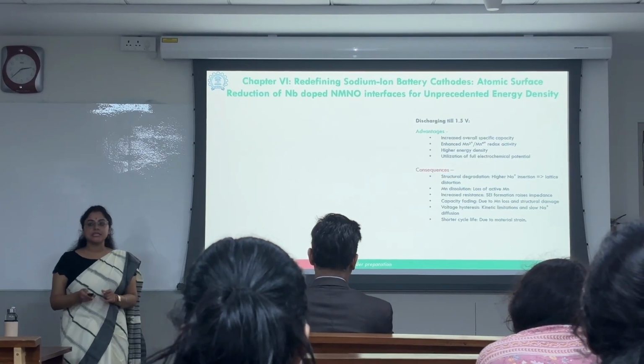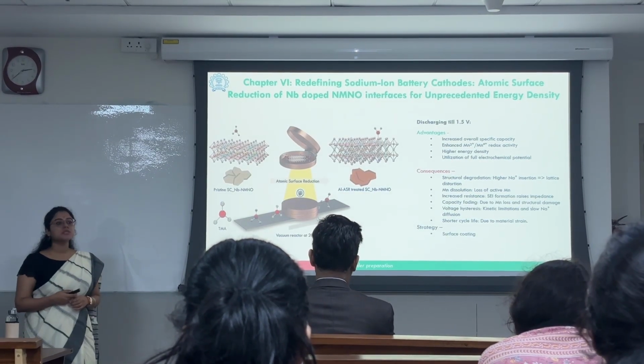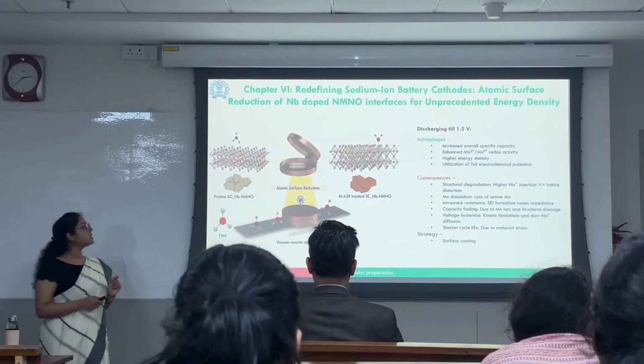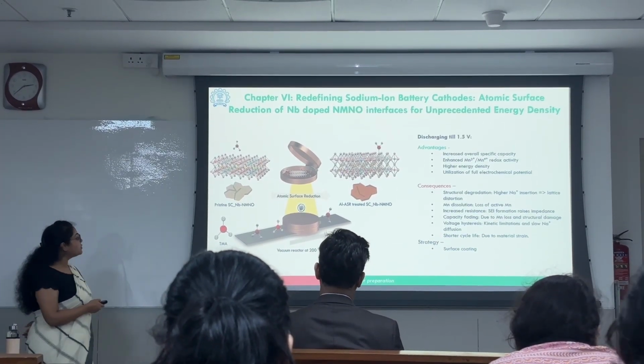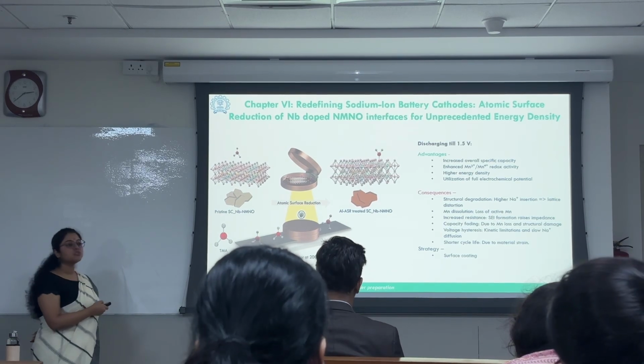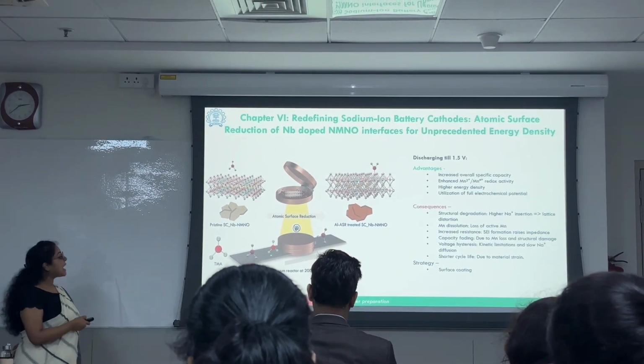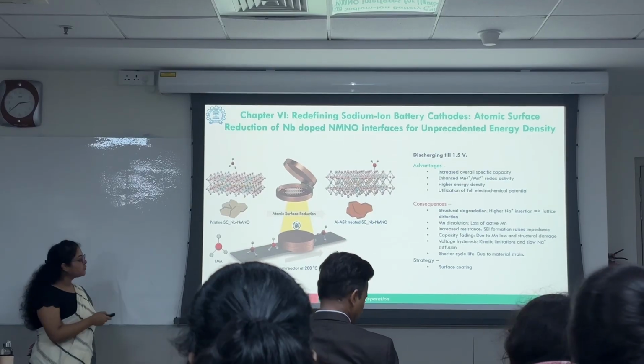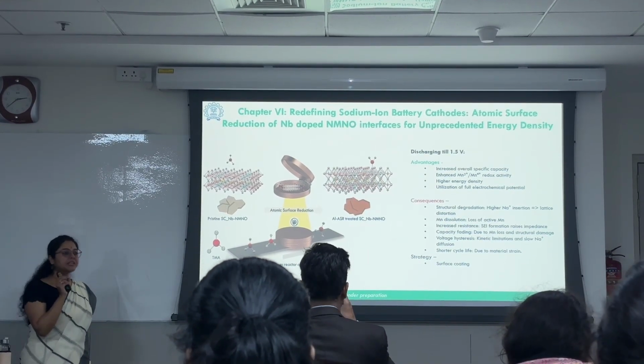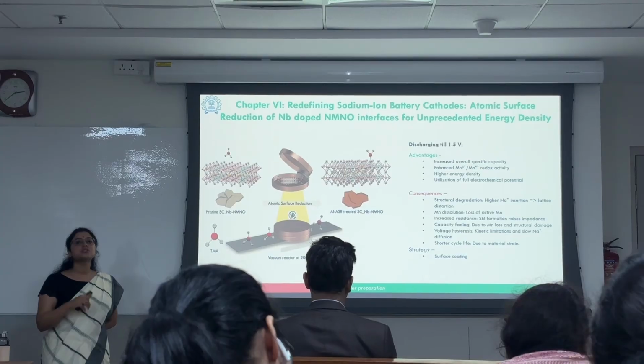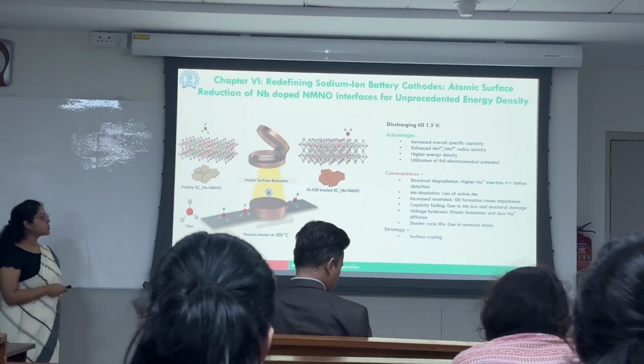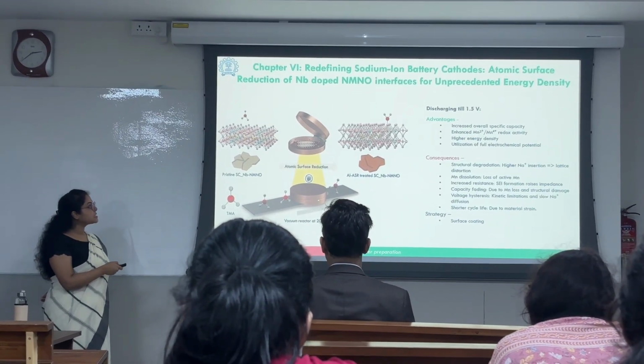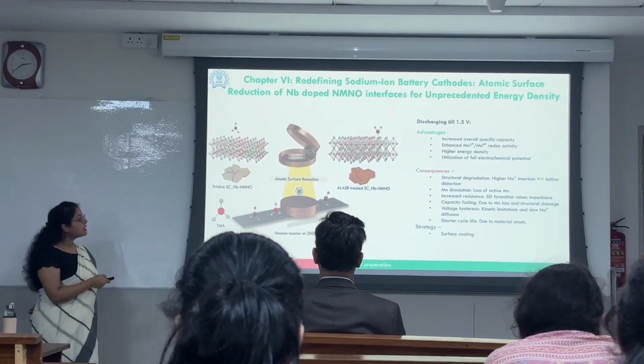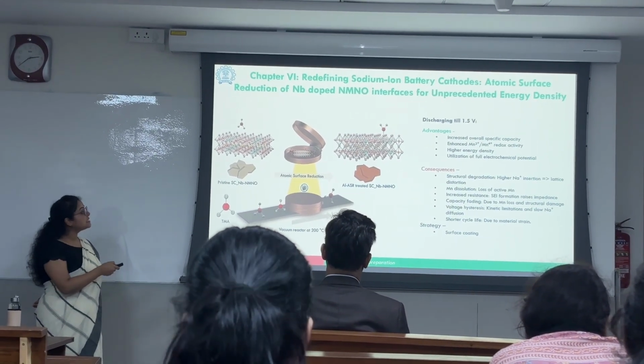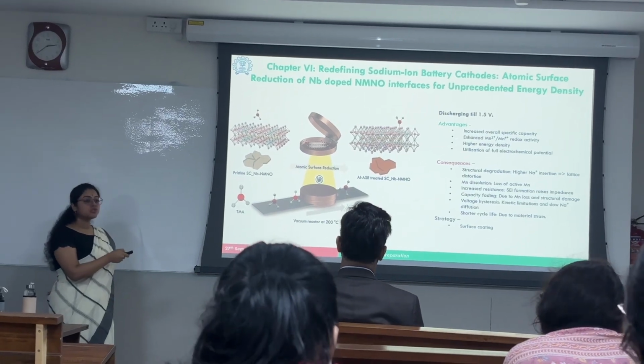In order to deal with this, we adopted the strategy of surface coating through an unconventional atomic surface reduction technique, where we choose an organometallic compound, trimethylaluminum, as a precursor, and then pass it through the vacuum reactor at a low temperature of 200 degrees Celsius, which marks its advantage over the ALD, atomic layer deposition, technique. This vacuum reactor consists of the cathode material, and once it has been pulsed, we get an aluminum treated cathode material which gets attached to the plate.